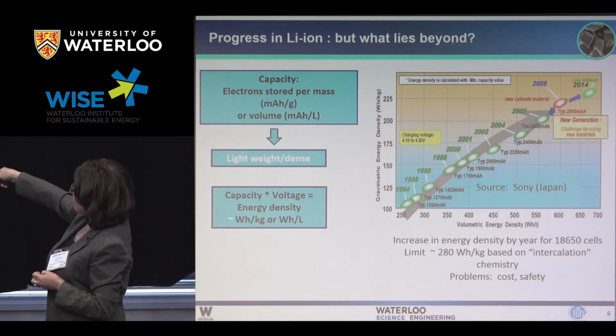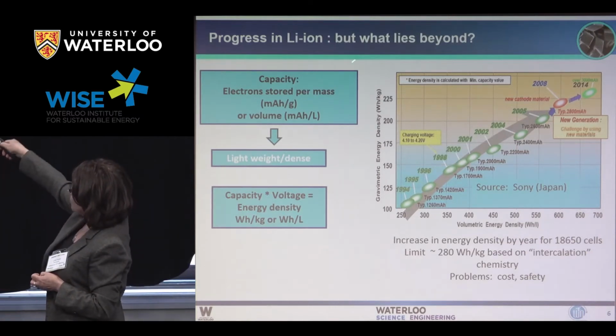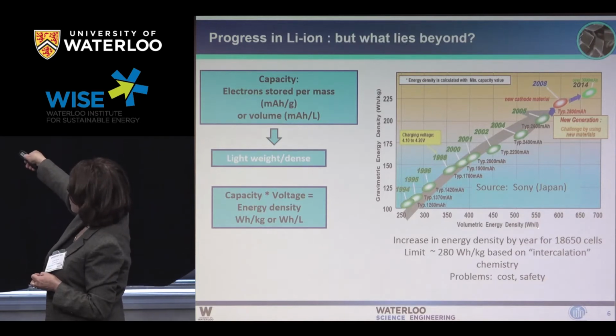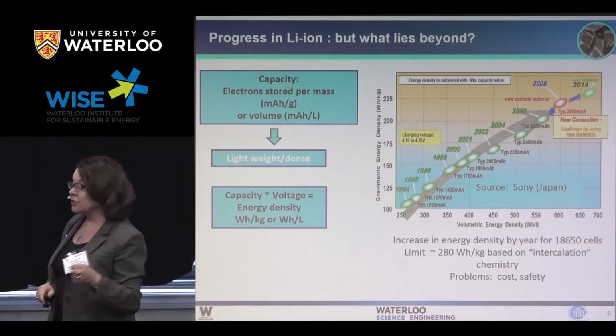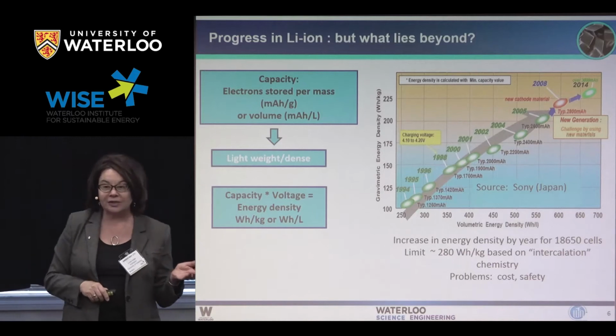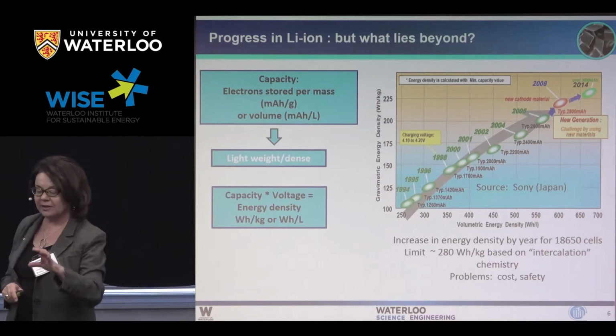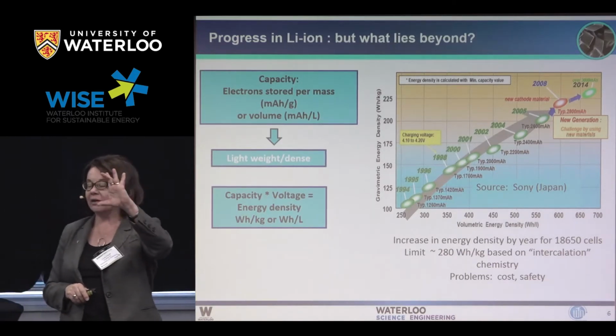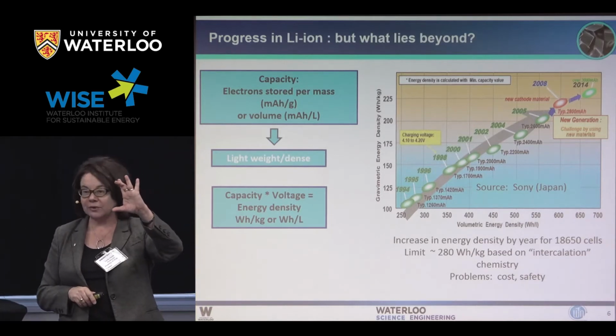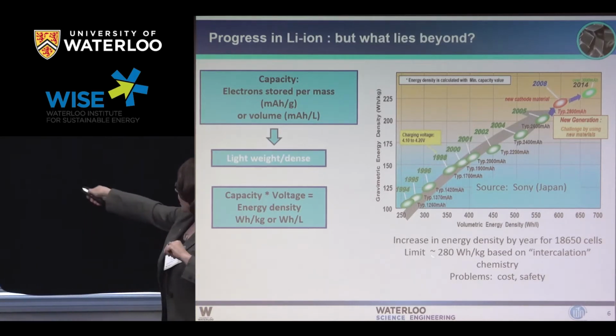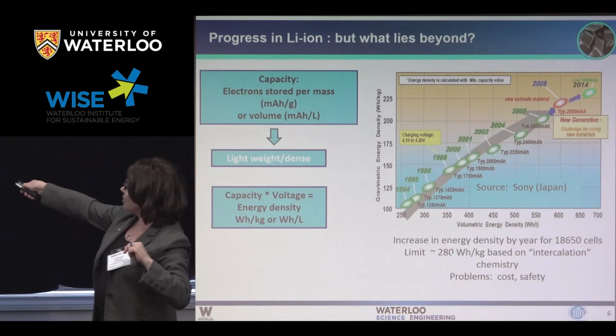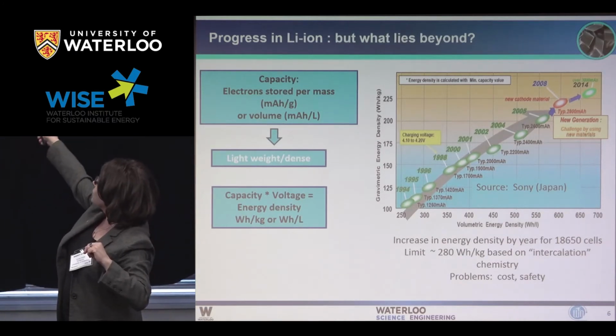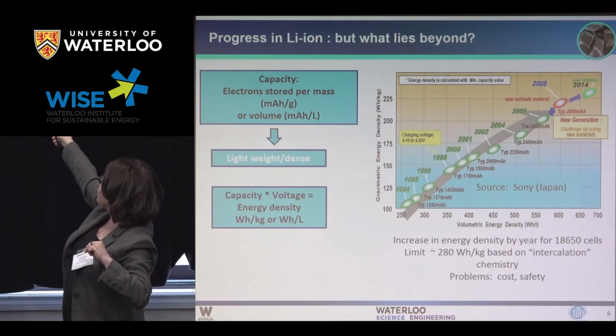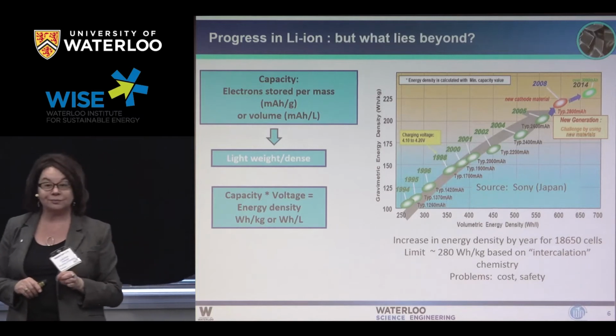And this plots the gravimetric, that is the watt-hours per kilogram, versus the volumetric in watt-hours per liter. So there has been an increase in density for these cells. We call them 18650 cells just because it's the size of the cell, and it kind of looks like a huge AA battery. And it is predicted that we're going to hit a limit of about 280 watt-hours per kilogram, which is up here somewhere, very soon.